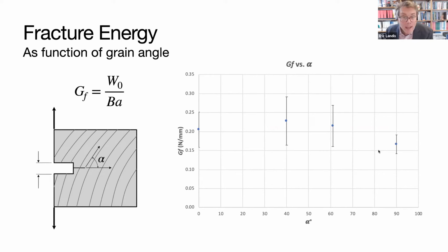And I want to emphasize that at 90 degrees, remember, we had all of this unstable crack growth. So in fact, we have no way to properly measure the energy dissipated because of the instabilities. So therefore, these values out at 90 degrees, we can say fairly conclusively, are an overestimate of fracture energy.